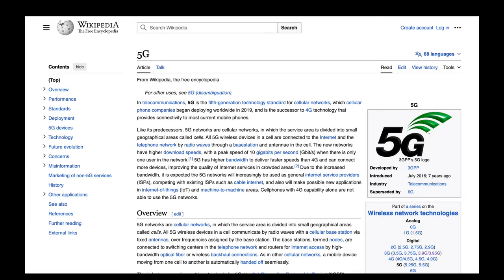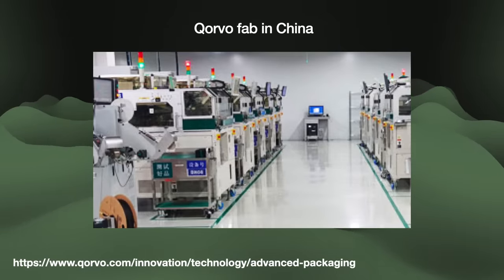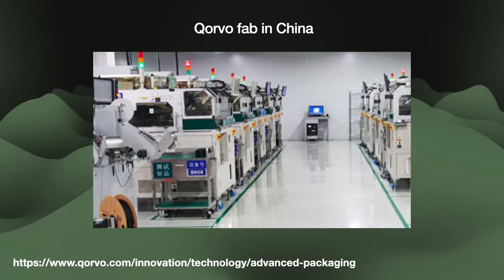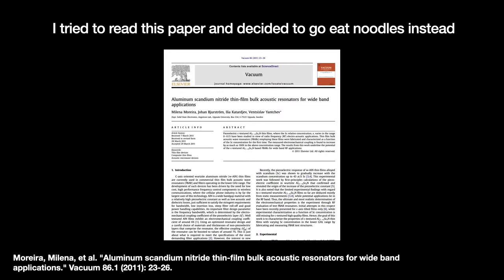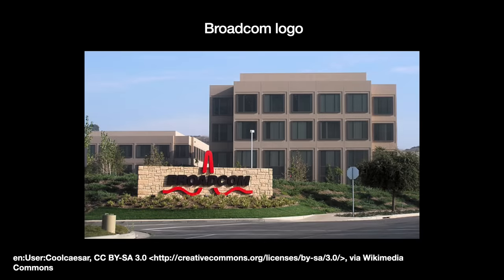LTE was a 4G technology and drove a huge boom. And now we are going into a 5G world. 5G can deliver significantly faster data rates than 4G devices, which in turn demands not only higher frequencies but also larger slices of those higher frequencies. So BAW filters need to adapt once again. An RF filter for a higher frequency needs to make the electrode-piezoelectric sandwich even thinner, and the materials might even have to change. One major concern has been the piezoelectric material used in the sandwich — for a long time that standard has been aluminum nitride. But the demand for bigger bandwidths has led companies to start doping scandium into the mix, which improves RF performance. The catch is that doping in scandium has manufacturing issues, leaving Qorvo and Broadcom to play a fun game of trying to figure out how much scandium they can add and get away with.